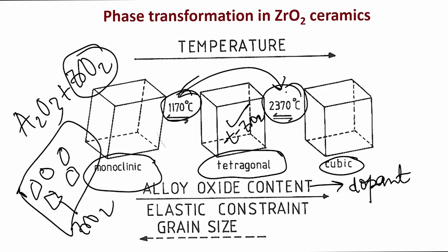But these zirconia particles are constrained in an alumina matrix. Now, alumina has an elastic modulus of 390 gigapascal, whereas zirconia has an elastic modulus of 210 gigapascal. By dispersing zirconia in an alumina matrix, essentially you are allowing the zirconia particles to experience larger elastic constraint in their neighborhood, because all the alumina grains which are part of the alumina matrix have higher elastic modulus, and accordingly, because of the elastic constraint, the high temperature tetragonal zirconia phase can be retained. So essentially it will not allow tetragonal to undergo phase transformation to the monoclinic phase.